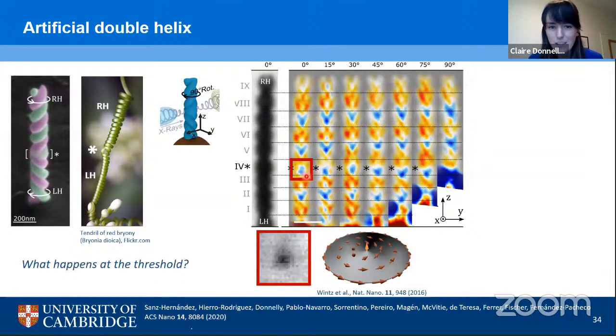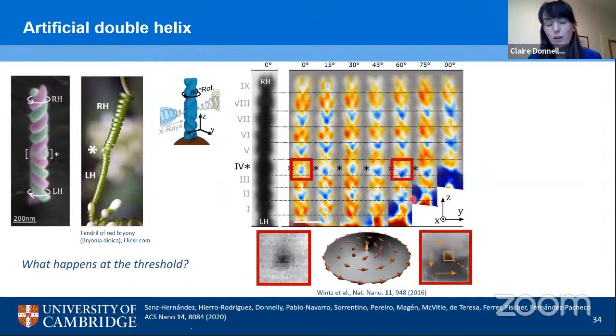When we look, for example, at 0 degrees, we see that we have this bright spot, so this blue spot, that is surrounded by the opposite contrast. Now, this is very reminiscent of the contrast expected from the out-of-plane contrast of a magnetic core of a domain wall. Now, when we rotate the sample, specifically at 60 degrees, we see that this contrast changes to, let's say, bright on the top and dark on the bottom. Again, mirroring the contrast that is known to result from a magnetic vortex.